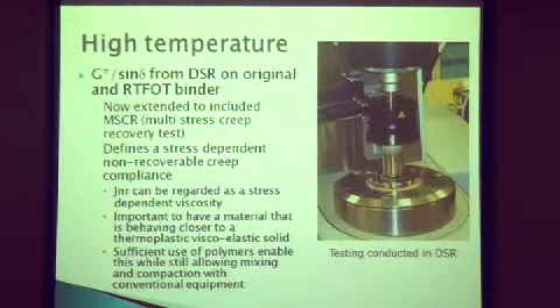It'll be a viscoelastic liquid if they're at minus 30 degrees. It'll be a viscoelastic liquid if they're plus 100 degrees. Okay? It's not until you start to put some chemistry in that, with polymer modification, cross-linking, that you start to convert that material to behave closer to a viscoelastic solid. Okay? So it's very important just to remember that all these binders are viscoelastic liquids.